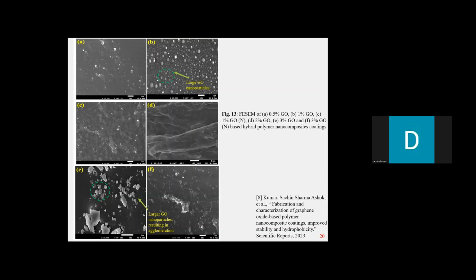For D, which is representing 2 weight percentage GO, it was pretty smooth. It actually covered all the holes that were in the coatings, and that's the reason why it provided a tortuous path effect to delay the electrolyte ions from penetrating through the metal substrate interface.